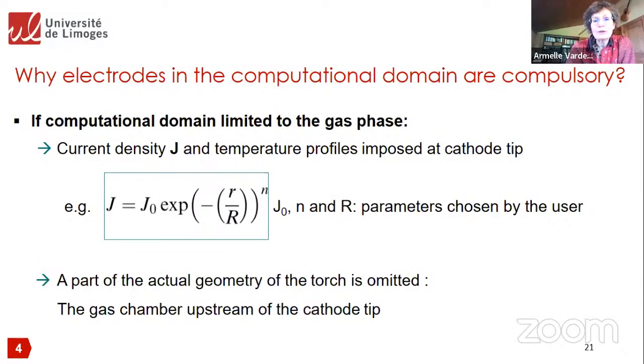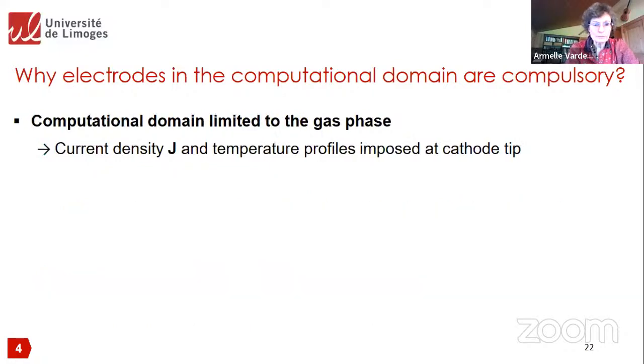this is a problem, because each time you change your process, you change any process parameter, for example the arc current or the gas, you have to select these parameters. And it's not so obvious how you have to select them. You need some experiments or experience and so on. Also, if you don't have the cathode, you omit some part of the geometry of the torch, and experience has shown that this will lead to some problems in the prediction.